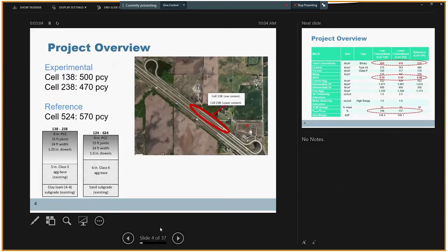So the test cells that we are talking about here are test cells number 138 and 238 at the MnROAD facility. We had two experimental cells. Cell 138 was cast with concrete prepared with 500 pounds per cubic yard of binder, and the second experimental cell, cell 238, was cast with concrete prepared with 470 pounds of cementitious materials per cubic yard. We call them cells with low and lower cement content. The data we have here are compared with the ones we got from cell number 524, which was a reference concrete and reference cell for us, and the concrete used for its construction was prepared with 570 pounds of cementitious materials per cubic yard.